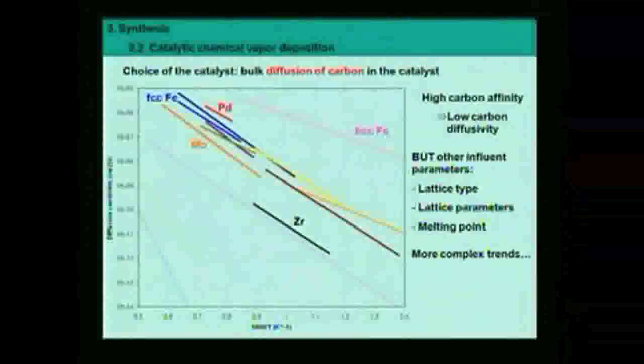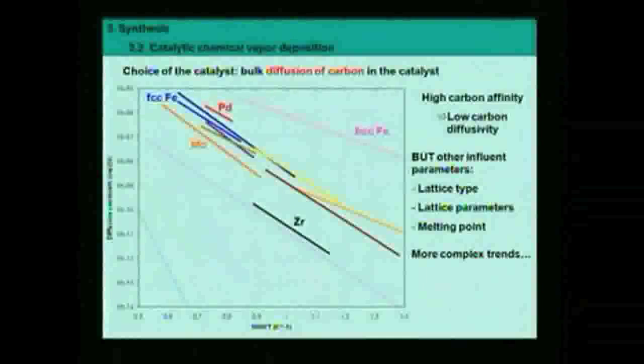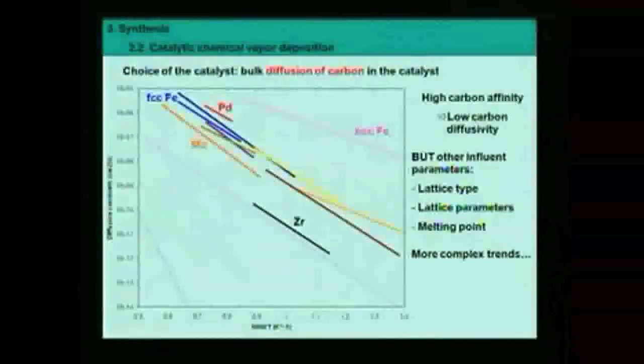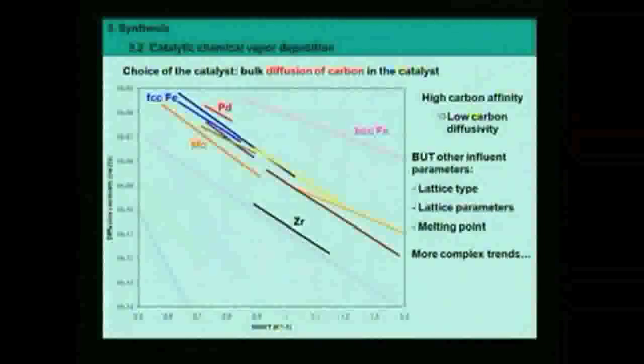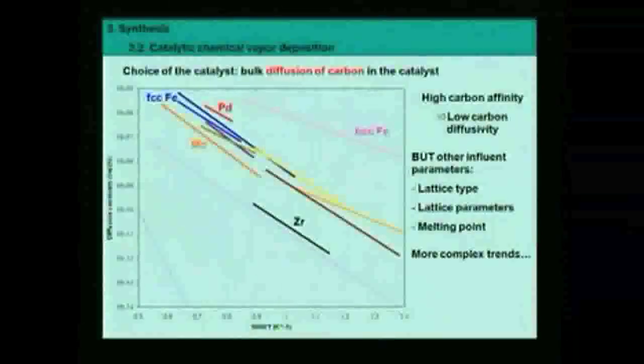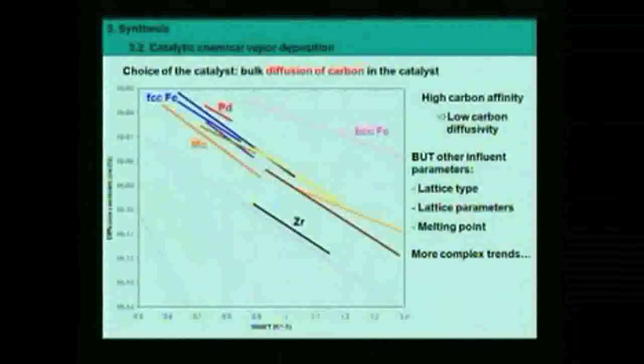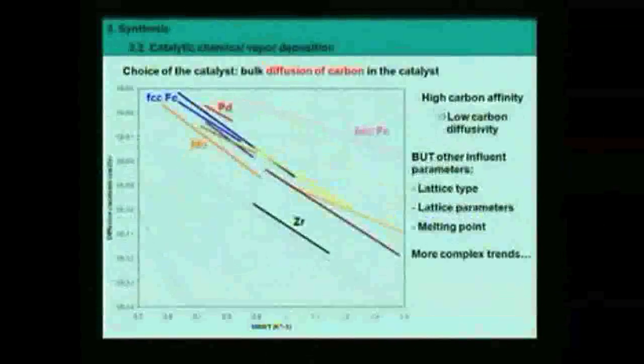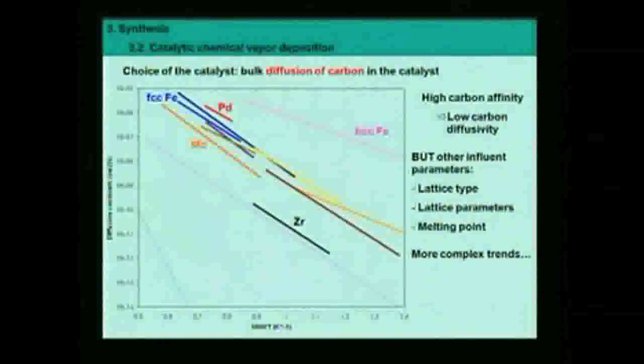So this is kind of observed. You've got this same trend. High carbon affinity gives a lower carbon diffusivity, but it is more complex than previously, where we were just considering surface reactions. Here, if we consider bulk diffusion, it's not only the strength of the bond between carbon and the metal which is important. There are other effects, because we want this carbon atom to move through a lattice, a 3D lattice of other atoms.